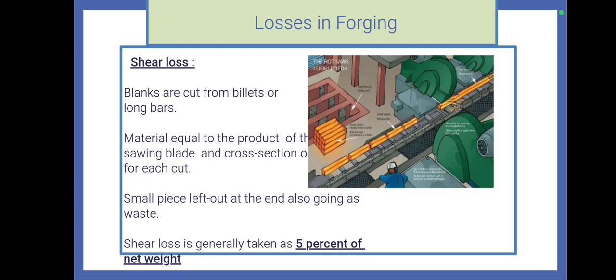Similarly, at the end of the billet, pieces of smaller dimensions are mostly left. These material losses are also included with shear loss. In general, the shear loss is taken as 5% of net weight.